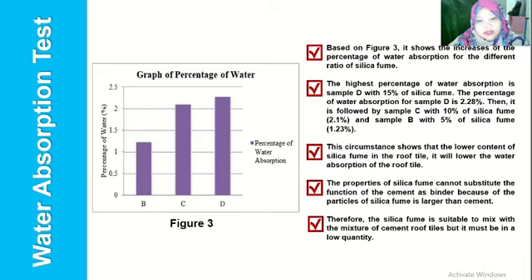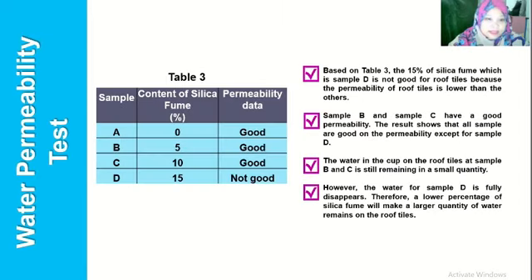This shows that the lower the content of silica fume in the roof tile, the lower the water absorption of the roof tile. The properties of silica fume cannot substitute the function of cement as a binder because the particles of silica fume are larger than cement. Therefore, silica fume is suitable to mix with a mixture of cement roof tiles, but it must be in a low quantity. Next is the water permeability test.